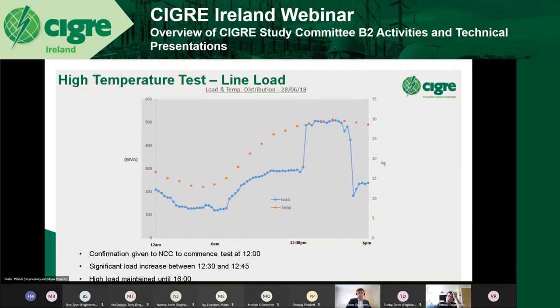This graph then just shows the load distribution and the ambient temperature on the day of the test. As you can see, the blue line, it was about 12:30, 1 o'clock, confirmation was given to the NCC to commence the test. So we hit 500 MVA in the line fairly quickly, and that high load was maintained for about 4 hours. Throughout that time, you can see the ambient temperature in orange there. We hit the hottest part of the day around 1 o'clock, which was near 30 degrees. So it did prove to be ideal test conditions for the test.